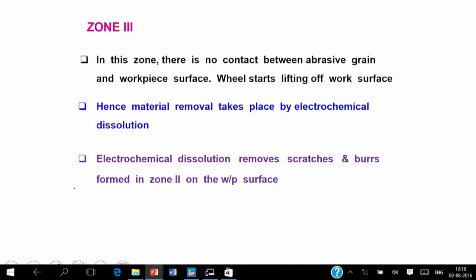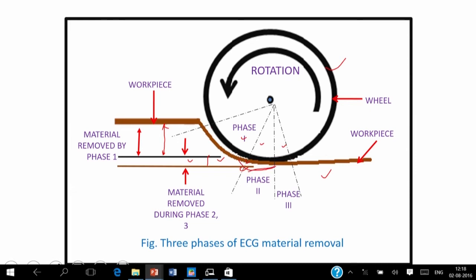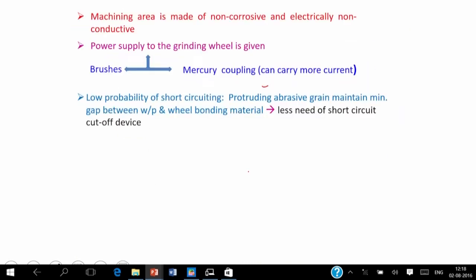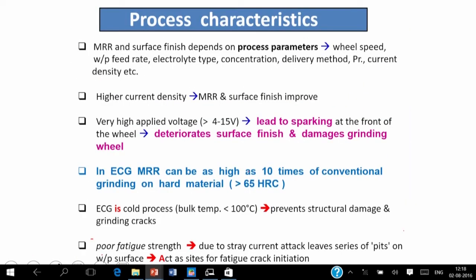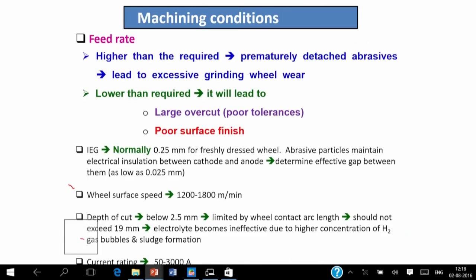The contact arc length we have already shown. So this is the contact arc length. If we increase the feed, this contact arc length increases. The wheel contact arc length should not exceed 19 millimeter. If the contact arc length between the grinding wheel and the workpiece is more than 19 millimeter, electrolytes become ineffective, because more hydrogen gas bubbles will be generated, with a higher concentration of hydrogen gas bubbles and sludge formation.